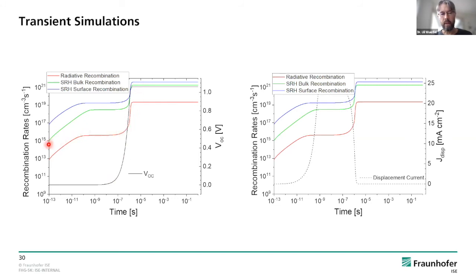Interestingly, you can see that we have now assumed impurity recombination, that is also called Shockley-Read recombination, via impurities in the bulk and at the surface. So it's a more complex model. Yeah, we do not only have radiative recombination, but you can see here that all 3 different recombination mechanisms start at the earliest time at a certain, rather low value, and then they grow, and then they seem to be constant for quite some time before they finally rise to their final values.